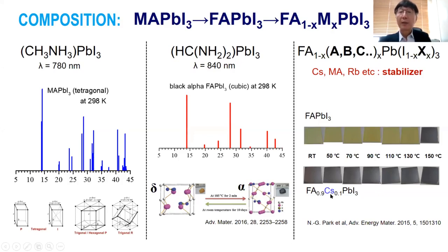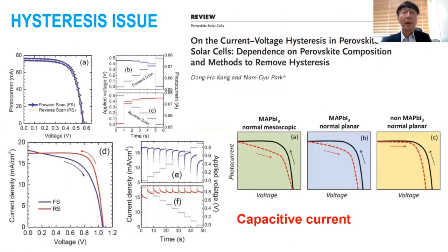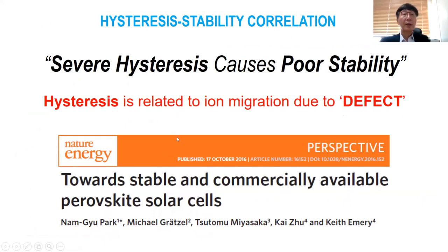So cesium, methyl ammonium, rubidium, the smaller cation for FAPbI3 is called the stabilizer. One unique property of the perovskite solar cell is the hysteresis. Hysteresis comes from the capacitive current at the electrode, which is quite dependent on the composition here. Recently, there are a lot of methods to solve the hysteretic behavior.